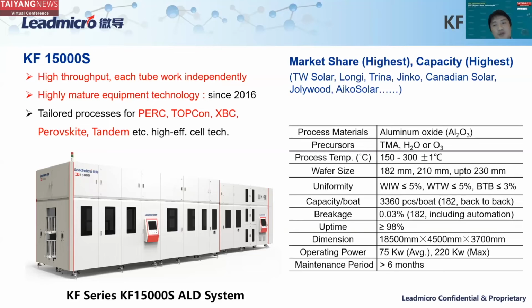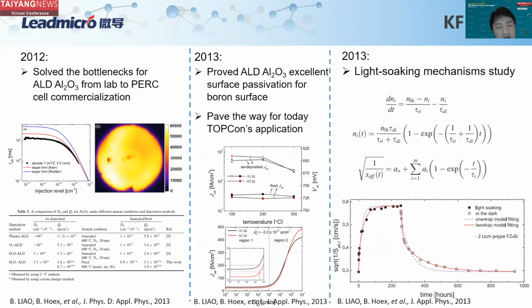Why did we have this breakthrough? Because we also have a very strong foundation that prepared us for the TOPCon era. From 2012, we had already resolved the bottleneck for ALD aluminum oxide from lab to PERC cell commercialization, mainly the firing stability issue. Back in 2013, we already proved ALD AlOx can provide excellent surface passivation for boron surfaces. That paved the way for today's TOPCon applications. Another important thing is that ALD aluminum oxide moved from the back side in the product time to the front side, the light receiving side.